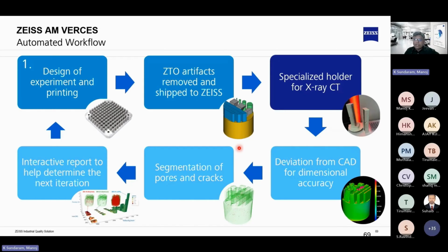We put it in a CT machine, and then once we measure it over a few days, or about 12 to 14 hours, depending on what kind of porosity you want, we are able to answer a few questions, like how is the deviation from CAD for dimensional accuracy? How good is your machine? How is the segmentation of pores and cracks?